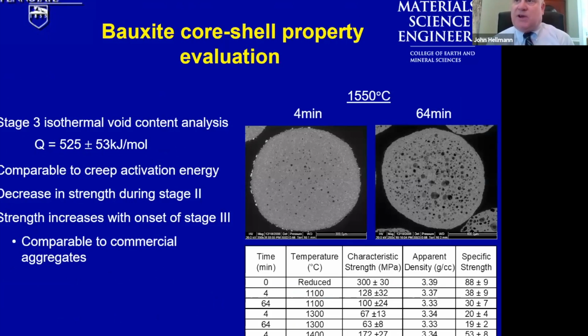Could we exploit those iron decorations to re-react with the material in subsequent phases of the sintering cycle to form a dense outer shell and a potentially porous inner core? And indeed, we were able to do that. And here's what we saw. If we started with a fully densified proppant particle achieved by our sintering process I just showed you, and then subsequently reheated it in a controlled oxygen partial pressure, we could evolve porosity in the interior of the particle while maintaining a dense outer shell.